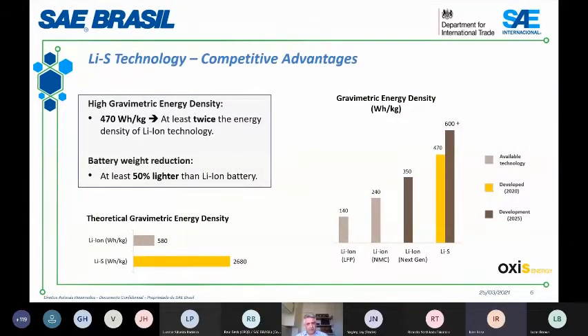Talking a little about competitive advantages of our technology is, of course, the high gravimetric energy density. I've already said 470 watt-hours per kilo, which is twice the energy density of lithium-ion technology, as we can see here. NMC, we can say about 240 watt-hours per kilo. And if we consider LFP, more or less 140 watt-hours per kilo. So it is more than 3 times its energy density. And if we think of future development, the next generation of lithium-ion technology, maybe we can say that by 2025 it can achieve 350 watt-hours per kilo. But at that time, we will have reached more than 600 watt-hours per kilo.